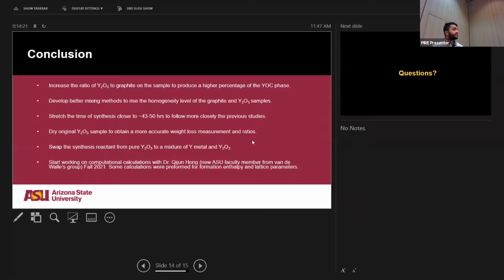Dry the original yttria sample to obtain more accurate weight loss measurement and ratios. Again, I used a weight ratio, so I'm going to do molar next time, and I'm going to try and dry the yttria. Now we had some problems with our dry boxes, so it was hard to work in non-moisture sensitive environments. And then finally swap the synthesis reactants from pure yttria to a mixture of yttrium metal and yttria. Yttrium metal is more reactive. It's also very moisture sensitive. So again, we need to develop better lab facilities in order to work on this stuff.